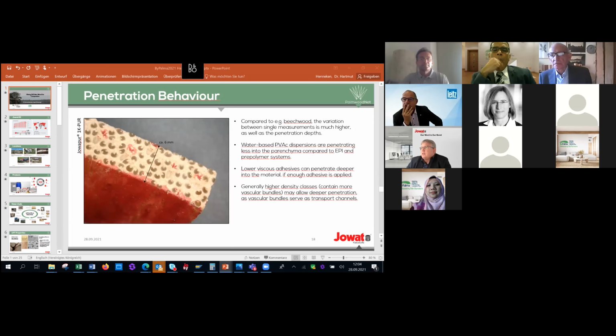So here's another picture of the cross section. These are samples made by the Schröder splitting saw that Mr. Kisselbach has presented. They are 6 millimeters in thickness, so you can see it's penetrating all the way through the 6 millimeters. So it's quite deep. It's much more than with other wood, such as beechwood, for example.